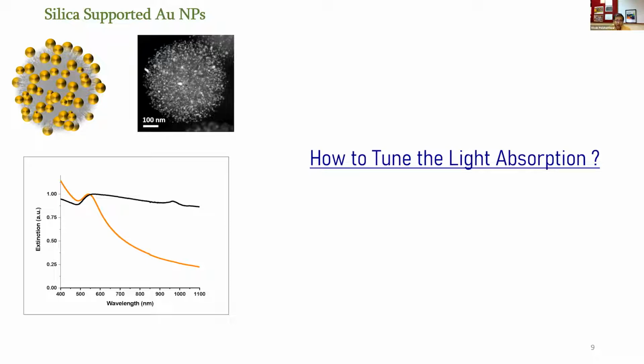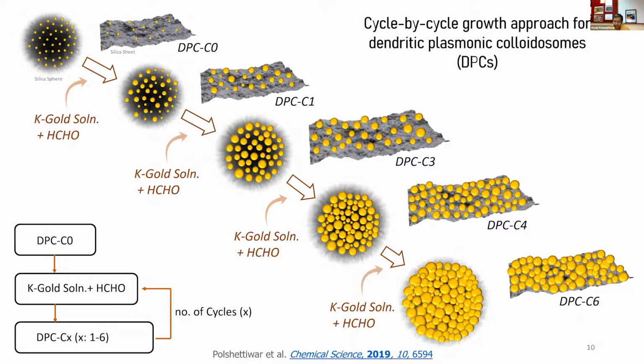Now the question is, how do I tune the distances between the particles? I can change the size, shape, morphology. We had some very nice presentations where others know how to change the shape and morphology. But how do I change the distance, that too on a solid support, because I want to develop a heterogeneous catalyst? So our hypothesis was that first let us load the silica sphere with the seeds of the gold nanoparticle. So these silica spheres, DFNS, are made up of these sheets or fibers. So you load these gold nanoparticles by a conventional method.